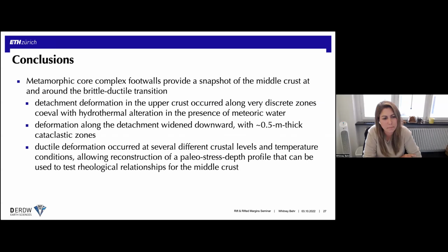Yeah, I want to say maybe Papua New Guinea would be a place where there's an active low angle detachment, and then there's definitely active low angle faults in Italy, in the Apennines, I believe. But it is a debated topic. There are certain groups that insist that these faults were never actually low angle, and another group that would argue that low angle faults don't produce earthquakes. But it's really clear from the structures that we see in the Whipple Fault that at least right around the damage zone of this fault there was seismogenesis associated with pseudotachylite generation. And I think there's evidence for that on many other normal faults as well. Thanks.